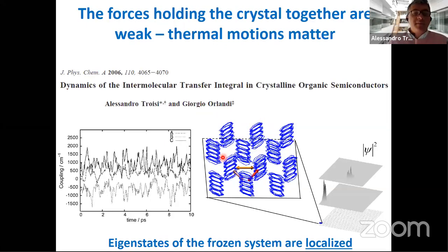In a very old paper, I think this was my first paper when I was appointed as an assistant professor, if you do a molecular dynamics simulation of a crystal and you compute as a function of time the transfer integral between two molecules, so the overlap between two molecules, the fluctuation due to thermal motion is enormous. It's actually almost as large as the average value of the coupling. The implication is that if you could freeze the crystal at one point in time and compute the eigenstates, those will be localized.